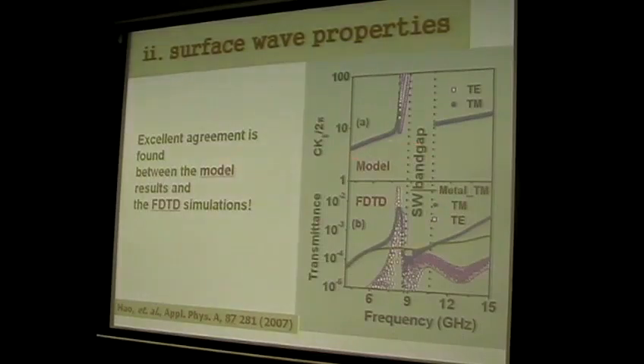This is a dispersion diagram given by the effective medium model of the double layer system, in which we predict a surface wave bandgap here, and also we have two bands here and here. And we performed an FDTD simulation to study the transmission on the realistic structure, and indeed we found a band gap shown here. So that demonstrates that this double layer effective medium model can perfectly describe the realistic structures.